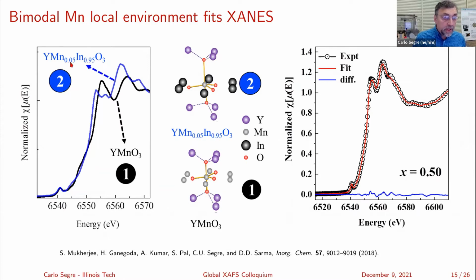However, when we get to the dilute case, now we have a situation where we have, say, one manganese surrounded by indium everywhere. And as we'll see later, with the indium surroundings the distances are much larger, the lattice parameters are larger. The indium occupies a bigger trigonal bipyramid, and so that manganese is sitting there and able to move around a little bit. In fact, you have a lengthening of the axial bond here, and this one is shortened. So you now have an off-center manganese, and that off-center manganese, because of the crystalline electric field, is what produces the blue color.